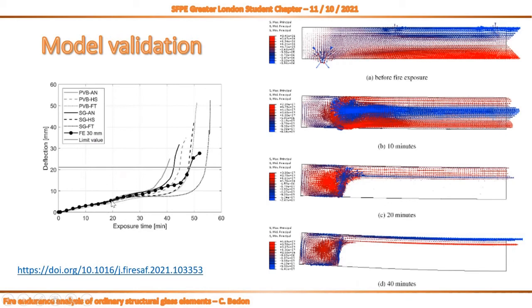After 20 minutes, we have a maximum deflection in the order of 7 or 8 millimeters, but a totally different configuration if you look at the principal stresses in glass. Again, the white region represents glass material with residual bending capacity against the mechanical loads. But if you look at the portion in white compared to the total size of the beam, you can also understand the reason of an increasing deflection even in presence of constant mechanical load on the top. So what happens from 0 to 50 minutes is just to keep a very small weight on the top of the beam and increase the temperature on the bottom.